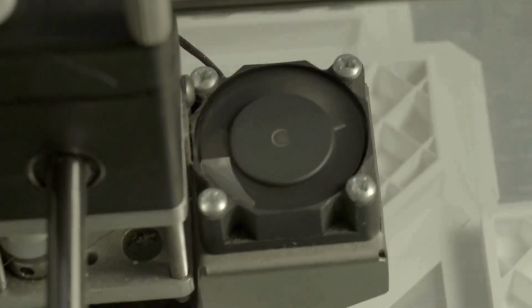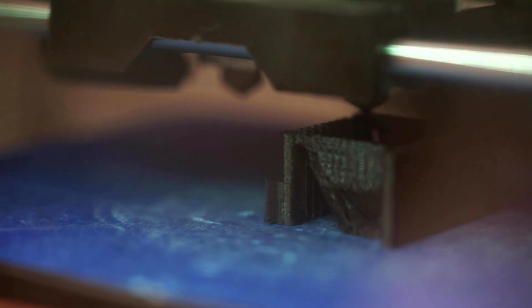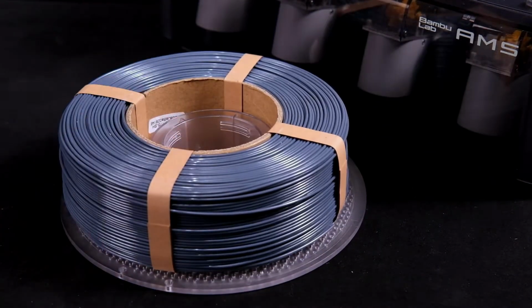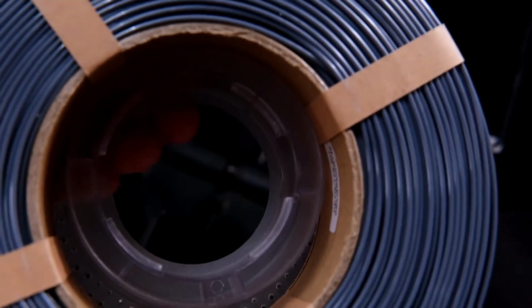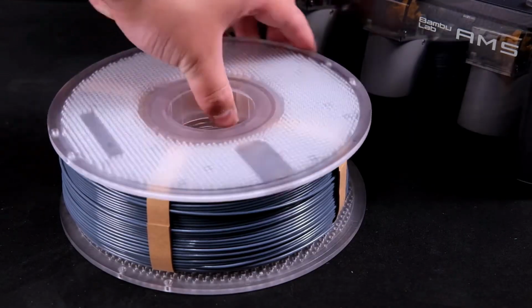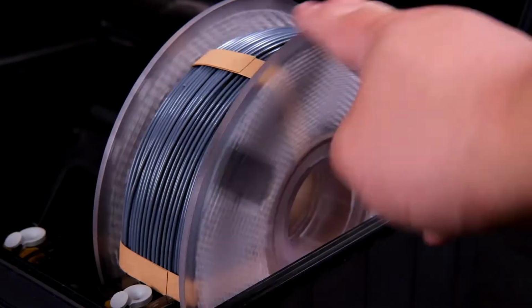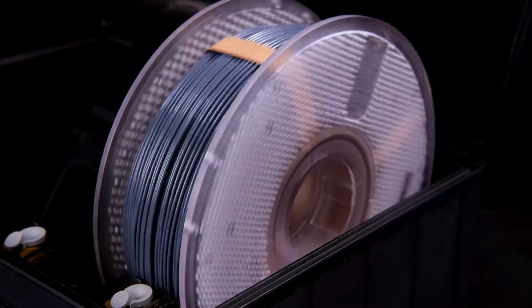ASA is more challenging to print with due to its higher temperature requirements around 240 to 260 Celsius and a tendency to warp. An enclosure is often needed to maintain a stable environment and reduce warping. ASA emits fewer noxious fumes compared to ABS, but still requires good ventilation.